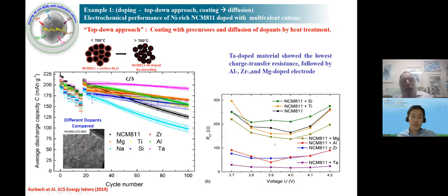I give you two examples of doping. And I tell you, doping is always both surface and bulk, no matter how you start. So there is the top-down approach. This is simple. You can take a metallic precursor, you choose the element. Here in the right chart, you see the results of cycling. You see also cross-sectioning where we did elemental analysis and we demonstrate the distribution of the dopants in the material.